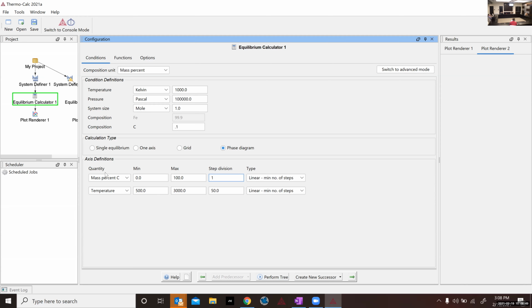My standard calculation is start at 500 degrees Kelvin to 2000 degrees Kelvin, because that's typically about the range where we're going to care. We're going to get low enough, and we're going to get up to the melting temperature. If we start doing something like refractories, obviously we may have to go up a bit higher. But for an iron alloy or for a nickel alloy, 500 to 2000. The wider you make those axes, the longer the calculation is going to take.